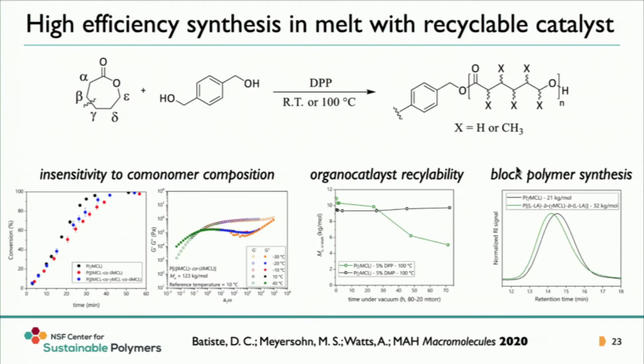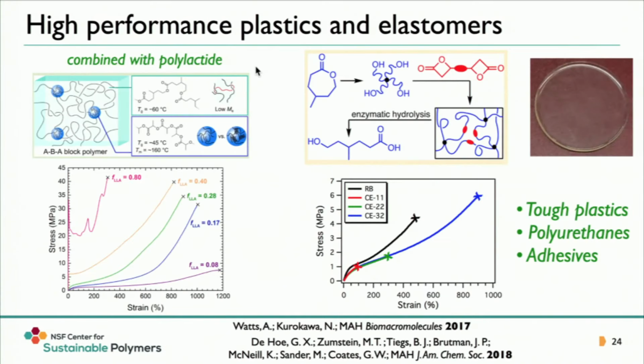And finally, they can be used in block polymer synthesis. And why that's important is because Annabelle Watts in my group a few years back combined polymethyl caprolactone with polylactide, which is a very common aliphatic polyester that's more of a plastic material, a higher glass transition temperature material, to make a suite of materials from soft elastomeric materials to tough plastic materials by including polymethyl caprolactone in this block polymer format. And that turns out to be quite useful for making tunable materials properties.